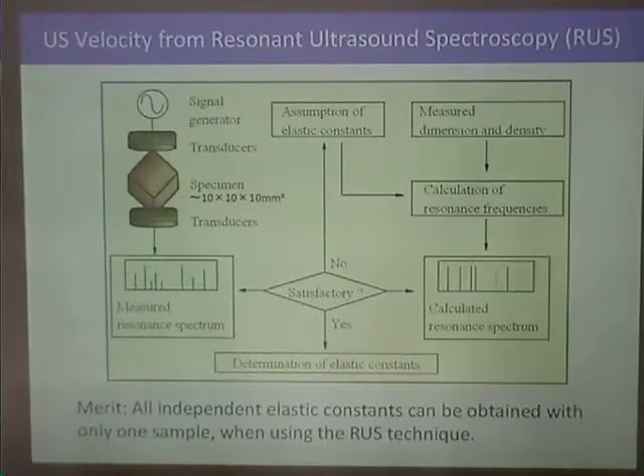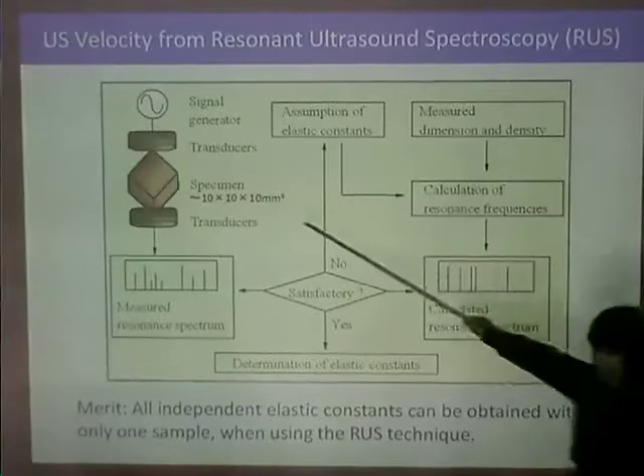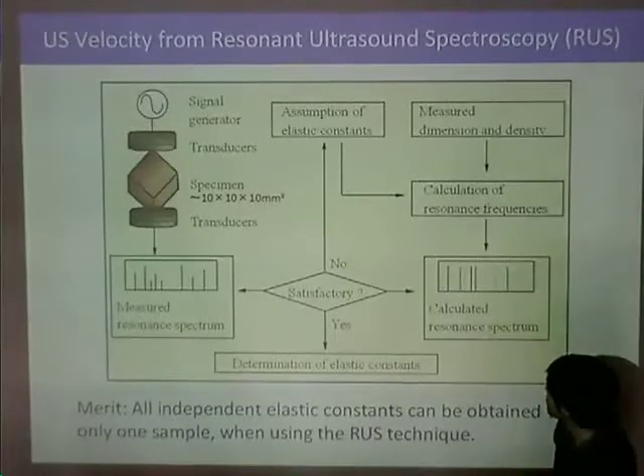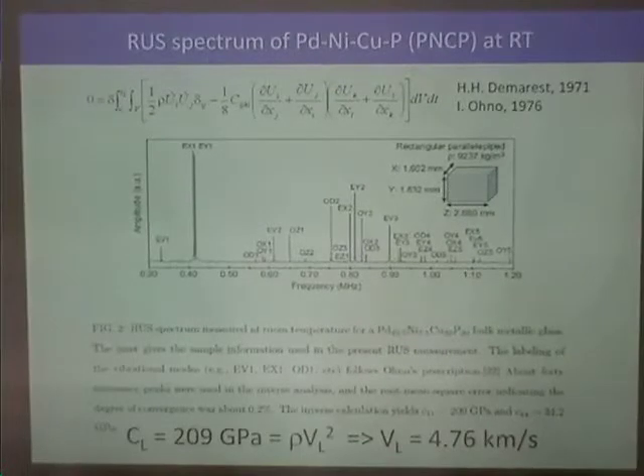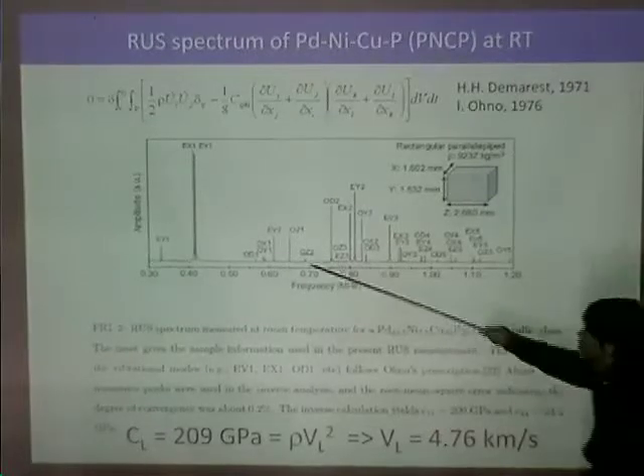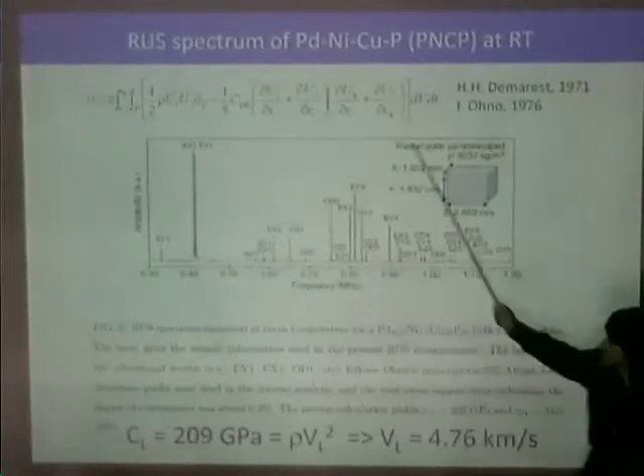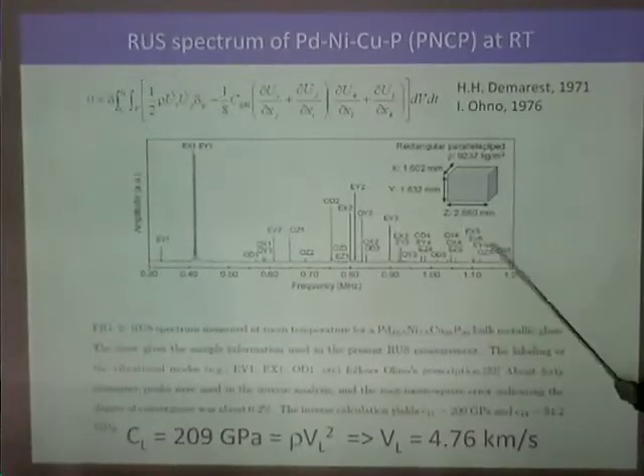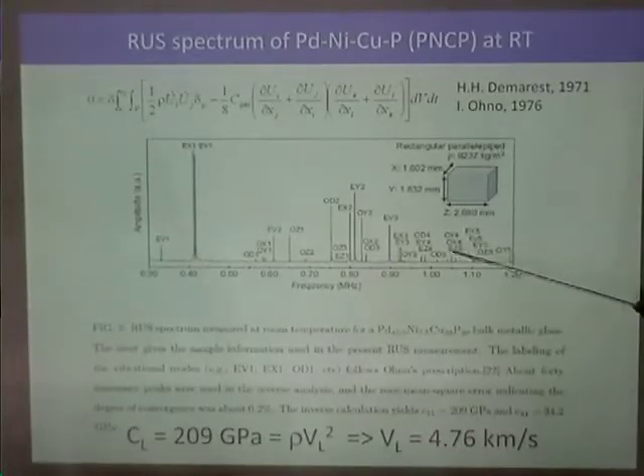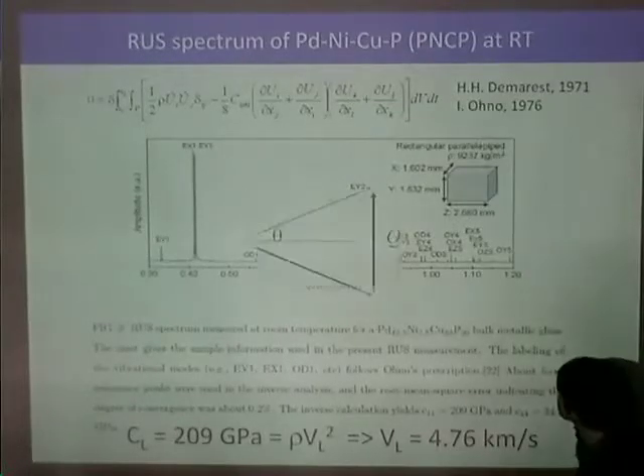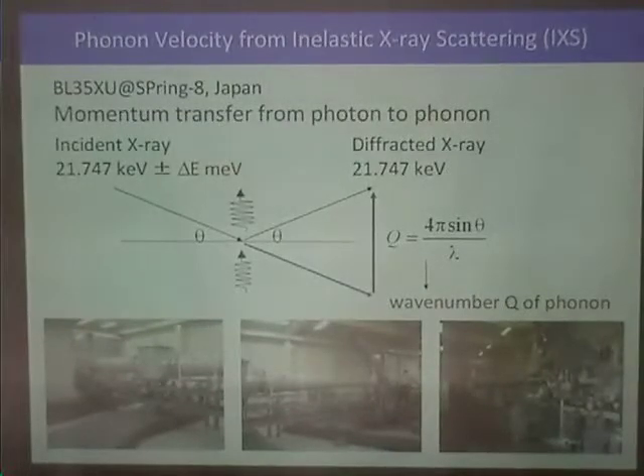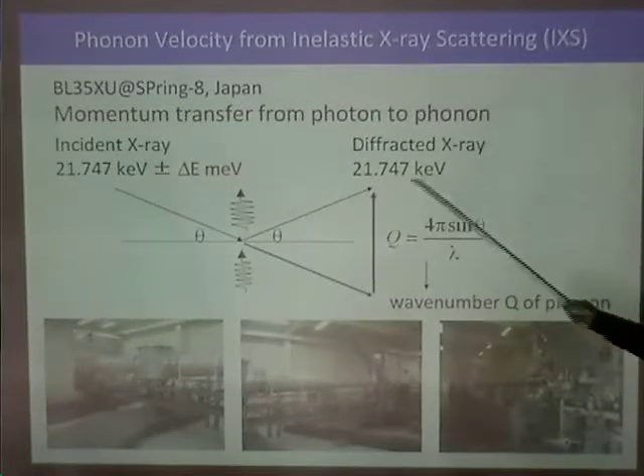So we have performed two experiments. One is the resonant ultrasound spectroscopy measurement, the RUS method. From the RUS measurement, we can obtain the resonant spectrum of the elastic medium, like this. From this elastic resonant spectrum, we can deduce the elastic constants of this material. And as to the phonon velocity, we have measured inelastic X-ray scattering at SPring-8 in Japan.